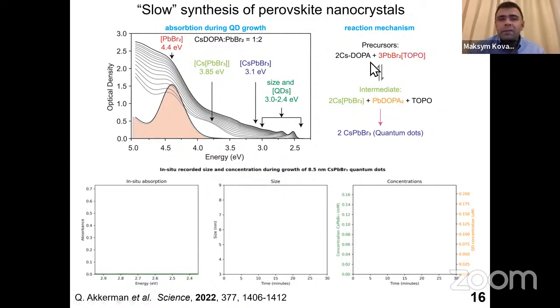Then, as you mix them, they slowly start to react, forming lead phosphinate of some kind, it doesn't matter too much, an actual intermediate. So now you form this cesium lead bromide, but not a lattice, but a conglomerate of ions, which is cesium plus and lead bromide 3 minus. It's a 3 nanometer large chunk of ions which are pre-aggregated, and then they slowly recrystallize into the nuclei of the nanocrystal, and then you form a nanocrystal. So that's our current understanding of the mechanism.